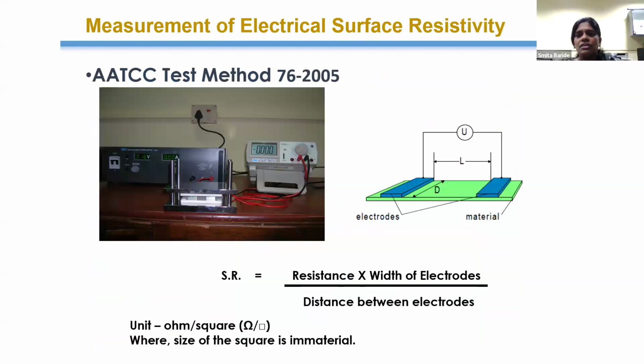The conductivity of the sample is generally measured in terms of surface resistivity. As I said in the earlier slide, our normal control sample has a resistivity greater than 10 raised to 10 ohms per square, that is, very high resistance. When we apply some conducting material over it, the resistivity drops. Conductive textiles are classified into two regimes: highly conducting and low conducting. Highly conducting textiles are generally used for shielding and smart textiles, ranging from 0 to 10,000 ohms per square.